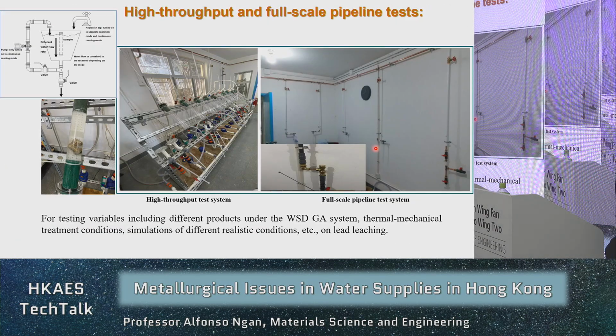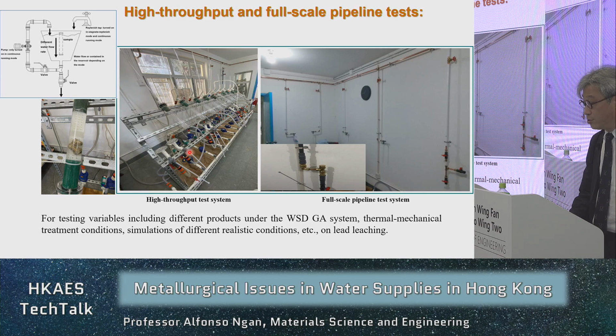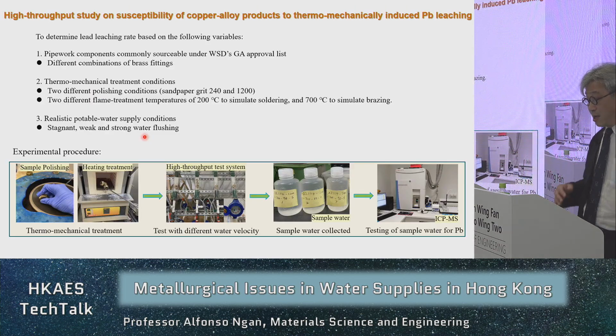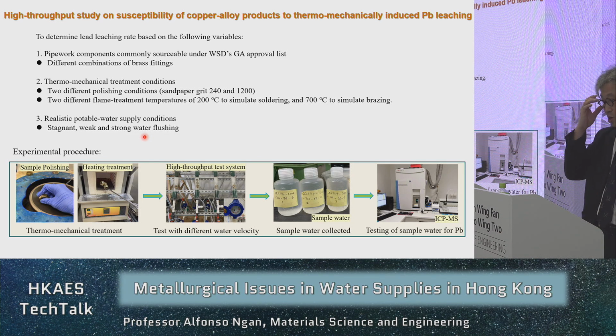Arising from that, this one is not supported by the Research Impact Fund. We built a high throughput test rig. This time not in a pumping station, but in another site provided by WSD. We built these test rigs, and in each one we have fresh water, not seawater, and then we have some brass component immersed inside. With this test rig, we can study a lot of different conditions, for example, the effect of polishing, the effect of preheating the workpiece, the water flow rate, and so forth. So that's our study scheme.